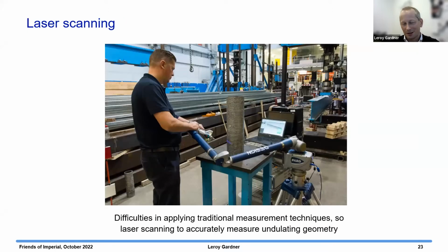A feature of this technology is that you get more geometric variability than you get with conventionally produced sections. And you can see some of the surface roughness, for example, on this tube. But we really wanted to capture the geometry as accurately as we could. You can't just use a vernier because the thickness and so on is different at all different points. So we used 3D laser scanning, and all of the sections were tubular.